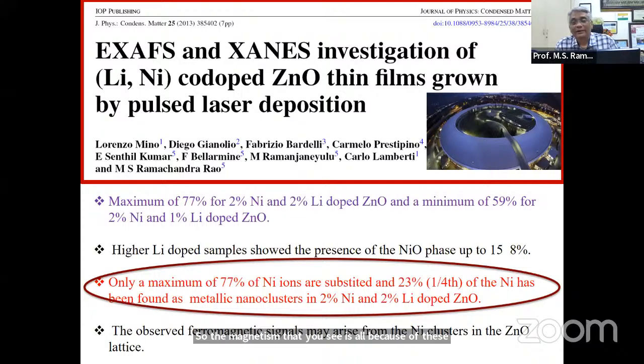In order to manipulate spin in a semiconductor, ideally you need a semiconducting lattice with a magnetic ion sitting in it. You can manipulate the spin, and you can think of making a spin qubit. But the problem is, even after 25 years of research, the only true magnetic system is manganese-doped gallium arsenide.